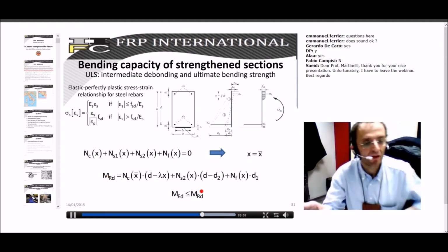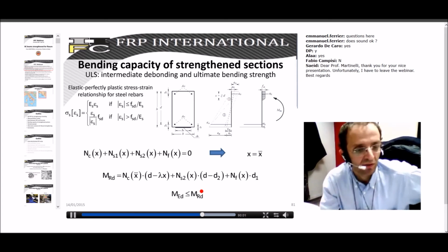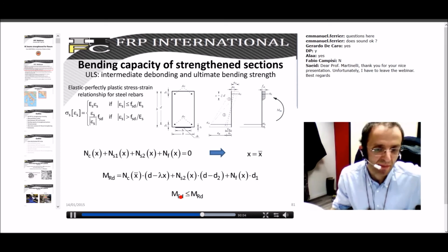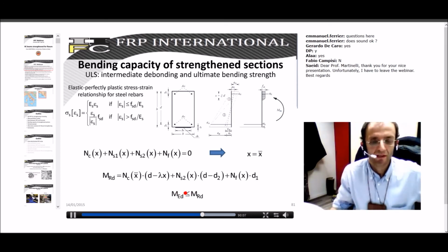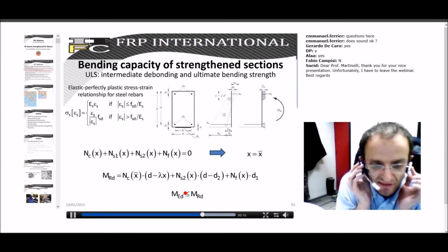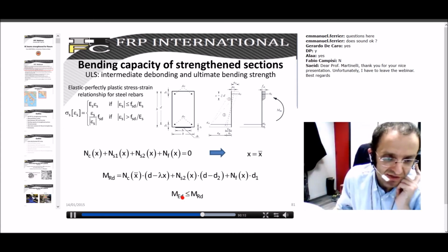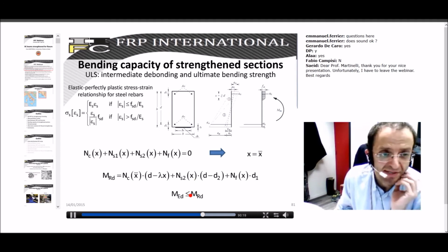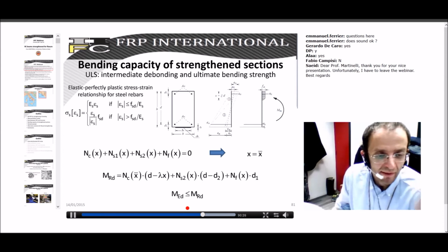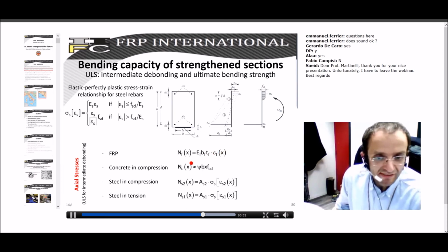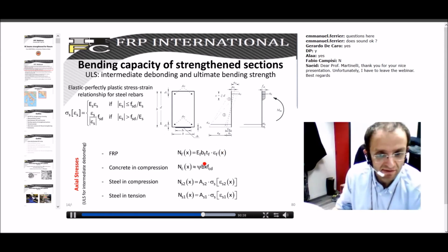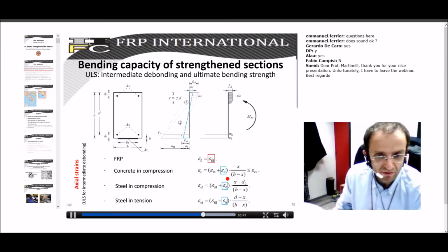Once you evaluate MRD, depending on the reinforcement, you have to compare this MRD with MED and check whether MED is smaller or bigger than MRD. If the former is the case, no crisis occurs at the ultimate limit state. It should be highlighted that MRD takes directly into account the possibility of an intermediate debonding crisis, because MRD is evaluated just taking into account that the maximum epsilon is lower than the epsilon FD, which is this one.